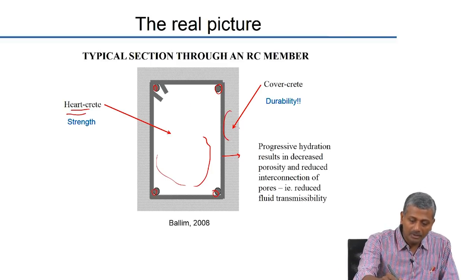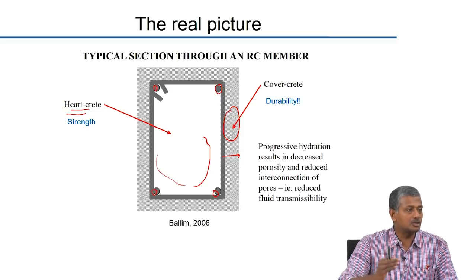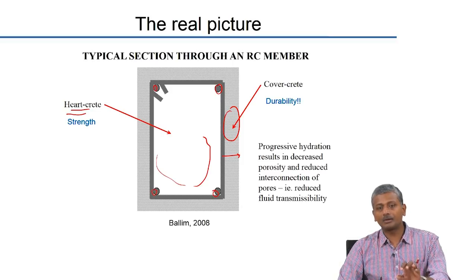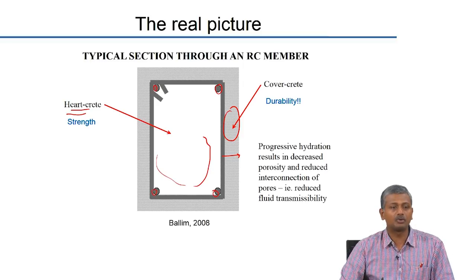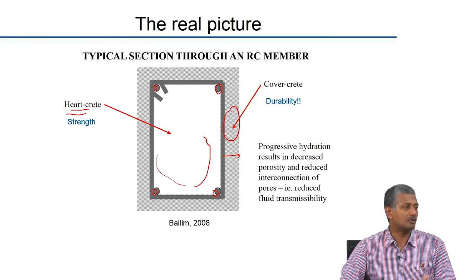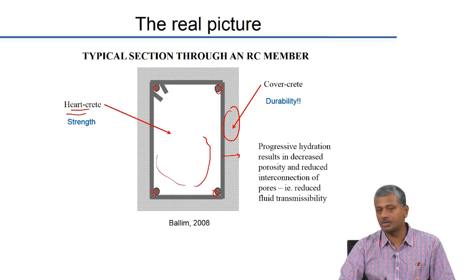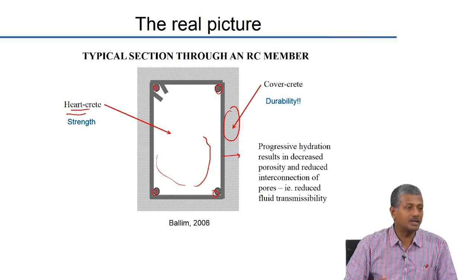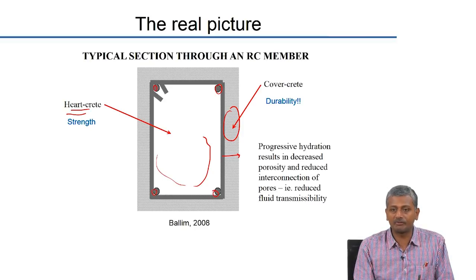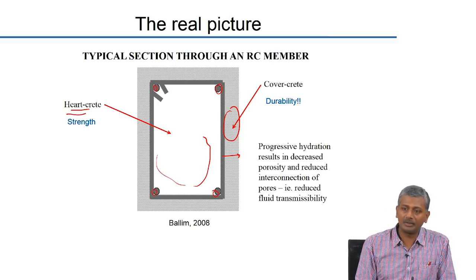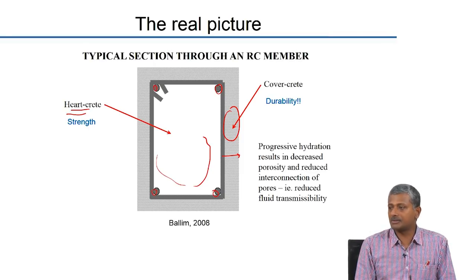But if you don't cure properly, the cover concrete, where we expect increasing hydration to reduce the permeability in the system, will keep on reducing in quality if you don't do a good job of curing. So curing has to be done from the point of view of durability. Here the curing is not affecting the strength of the column much, it is affecting only the durability very much. So the assumption that as long as the strength of concrete is okay, the durability should also be fine is not a correct one. We need to ensure that concrete durability is also maintained by its own set of parameters, rather than just worrying only about the strength. So strength based design needs to be augmented by durability based design to ensure that we get a structure that is long lasting and has the long term performance that we want.